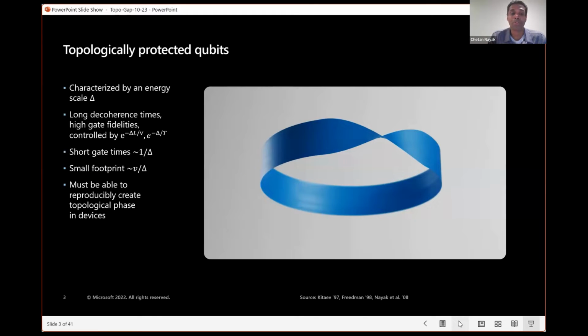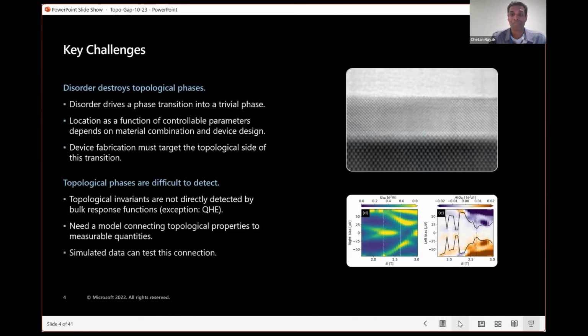You must be able to reproducibly create a topological phase in devices. Okay, so that puts a challenge right up front. Being more specific about what those challenges entail, the two key problems I would say are, disorder destroys topological phases. So they drive a phase transition into a trivial phase. The location of that transition as a function of controllable parameters depends on the material combination and device design.